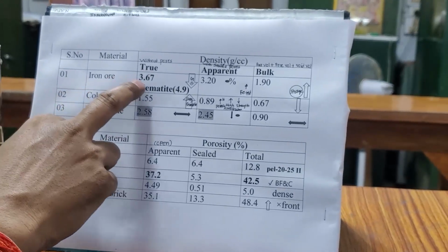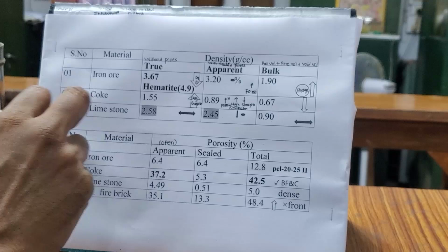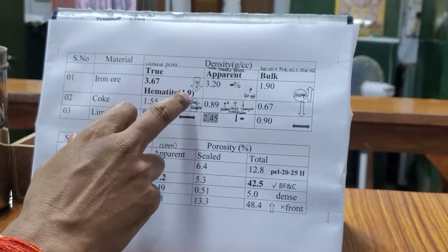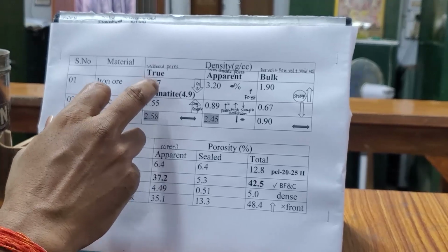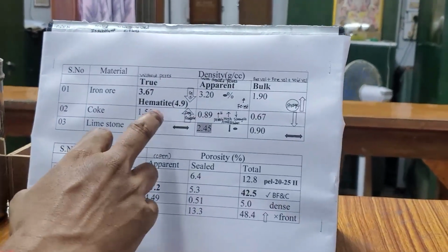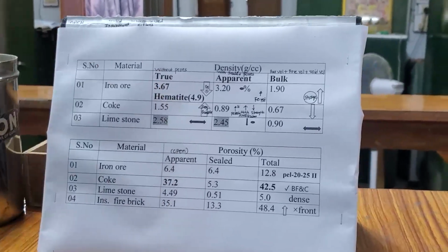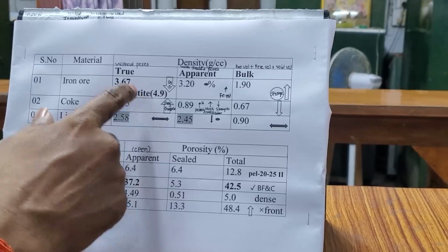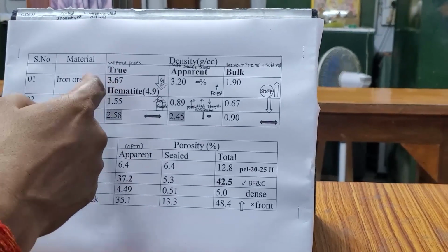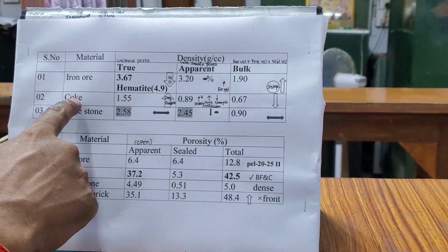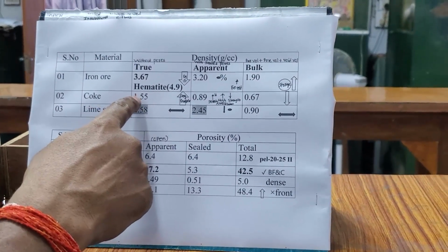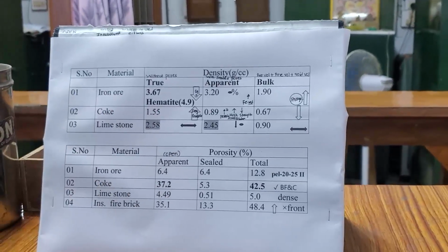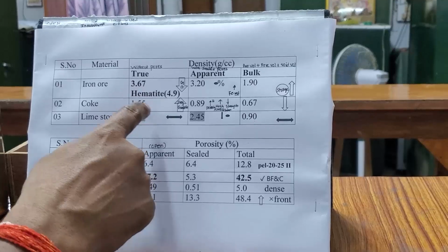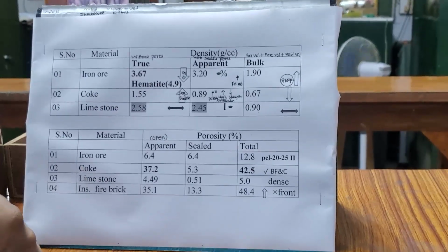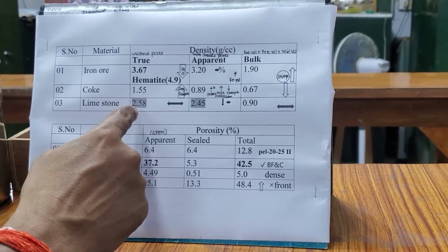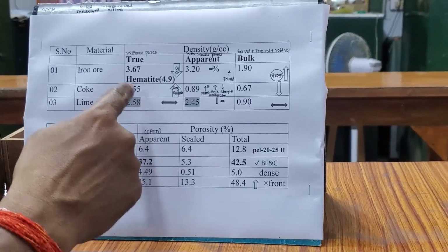In iron ore, the true density we got is 3.67. The true density of hematite is 4.9. So this 3.67 is nearer to this value. What does the true density of iron ore indicate? It indicates the percentage of iron ore is more. So the true density of iron ore decreases with increasing gangue content. In case of coke, the value of true density is 1.55. The true density of coke gives an indication of the degree of graphitization. In case of limestone, the true density is 2.58. That is in between the iron ore and coke.